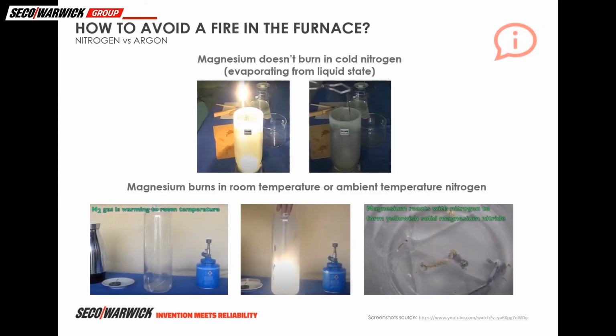As you already know, the ignition of magnesium powder takes place at a temperature of 470 C. To prevent this, it's needed to use a fire extinguishing system in the furnace atmosphere. The AMS 2768C norm referred to the NFPA 480 standard, allowing the use of nitrogen in a furnace atmosphere to do that. We decided to check it out with our R&D department.